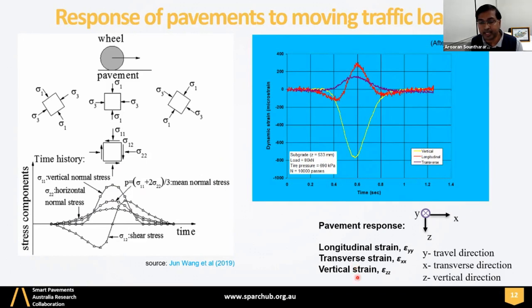But one interesting thing to notice here is the longitudinal strain, which is important for the bending of the asphalt and cement treated base. So what happened to the longitudinal strain and the transverse strain? EYY and EXX, basically Y is the travel direction, in other words the longitudinal direction, and the transverse direction is perpendicular to the travel direction, in the X direction. You see the strain value in the longitudinal direction is higher than the value in the transverse direction. That means the strain experienced by the pavement in the vehicle movement direction, in the horizontal direction, is higher than the strain experienced by the pavement in the transverse direction.